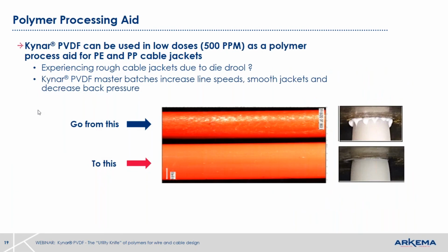We're coming to the end here. PVDF is also used as a processing aid, especially for polyethylene or polypropylene jackets. So should you have a melt fracture, like you can see in this top photograph, in your polyethylene or polypropylene jacket, the addition of an extremely small amount of PVDF, we're talking 500 parts per million, will turn your jacket from having melt fracture to none at all.